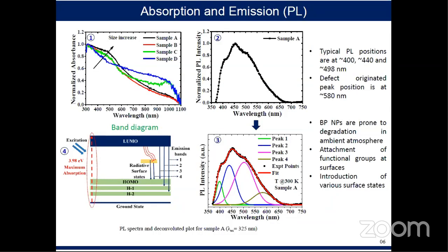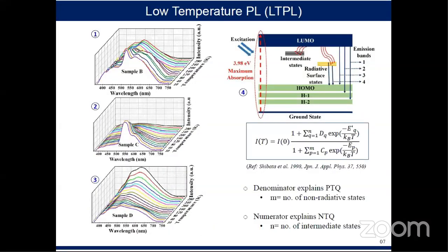Okay, so next slide. To know the exact role of the different functional groups, we performed time-dependent and temperature-dependent photoluminescence spectra for nanocrystal samples B, C, and D. Samples B and C have shown positive thermal quenching behavior, but sample D has shown negative thermal quenching behavior.